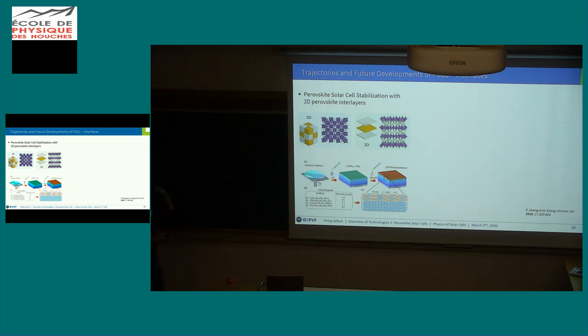It has the big advantage that these long chain molecules constitute an organic surface that is terminated with a closed shell electronic system. So it's not easy to attack the system chemically, and hence it leads to passivation of films. Also, the 2D perovskites, you can already see this from macroscopic material, are way more stable than 3D variants.